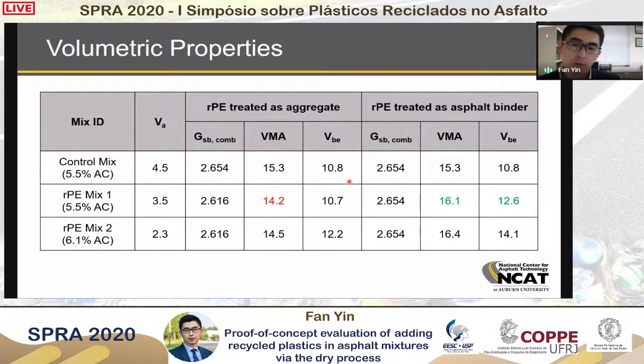But if we go to the other extreme, saying, okay, let's assume all the plastic goes into the binder. In this case, the Gsb of the aggregate remains unchanged, and all the plastic is going to be counted inside the binder. And then we do the calculation, and we get a much higher VMA on the plastic modified mix. And the same thing for VBE. So this result can be very misleading, since if we only look at those volumetric parameters, we may think, oh, we got enough binder in the mix, which should give us very good cracking and fatigue resistance. But those volumetric properties may not be fully reliable because it considers the plastic as part of the binder. In reality, that may not be the case.